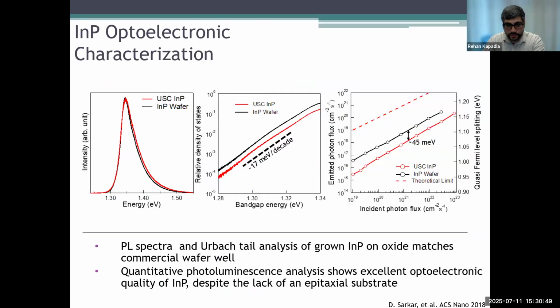So then you can go ahead and do optoelectronic characterization of these materials. What we're showing here is a comparison between what we're growing on and what a straightforward indium phosphide wafer looks like. That's what we think is the correct comparison here, because it's really like we're growing a bulk substrate. So these are typically on the order of hundreds of nanometers to maybe a micron thick. And we show that there's similar-ish behavior. It's not exactly the same, though the single crystal wafer is better, but it's definitely quite similar, and it's something that is not possible by using a standard vapor phase technique. You just can't do that.